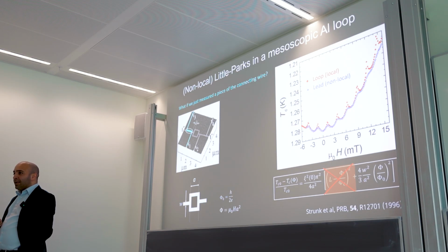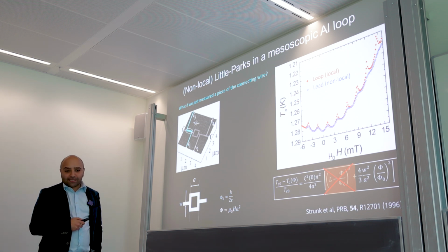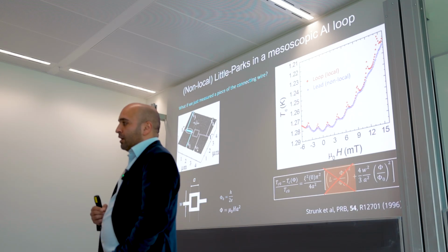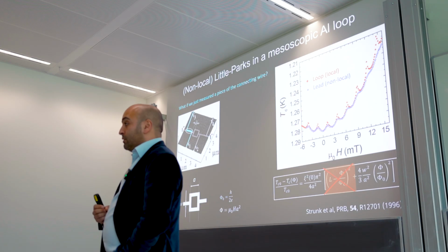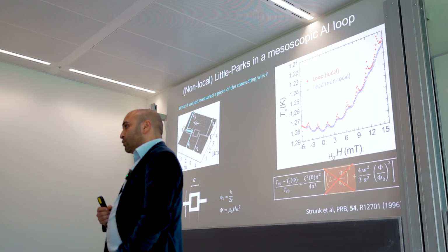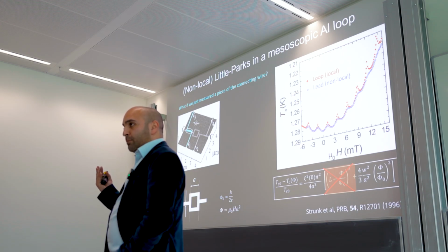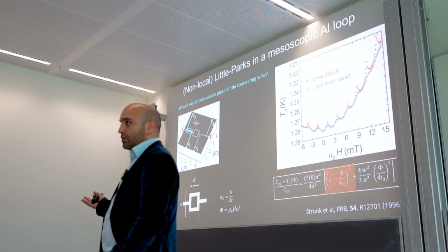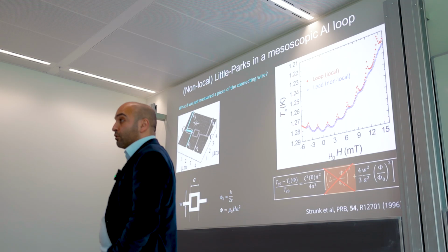The reason is, remember what we talked about in terms of length scale? That there are two important length scales, right? One was the penetration depth, but the other one was the coherence length. Now, what happens when you get a lower Tc? Well, the amplitude of the order parameter goes down. And this is a very strange thing about aluminium. Aluminium has the largest coherence length of all superconductors. It's freakishly large, basically 1 or 2 microns.